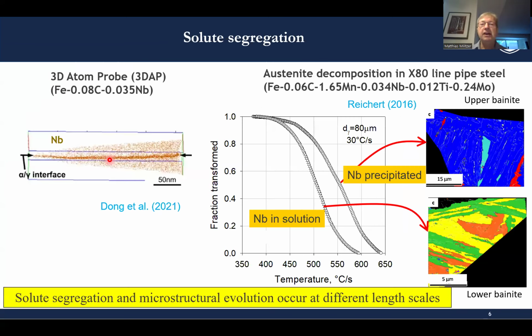Okay, so if you look at what happens on the scale of the interaction of solutes with the interface, I'd say that niobium is a particularly important microalloying element. We now have both experimental tools as well as modeling tools to deal with atomistic resolution. What is shown here is a 3D atom probe result of niobium segregation at the alpha-gamma interface. That's work by Dong and co-workers at Tohoku University, for a model alloy with